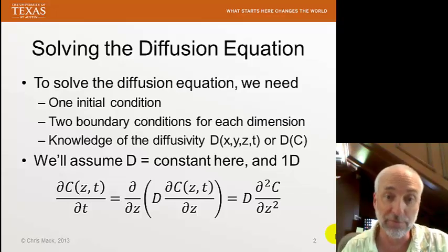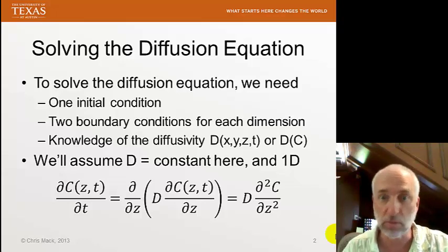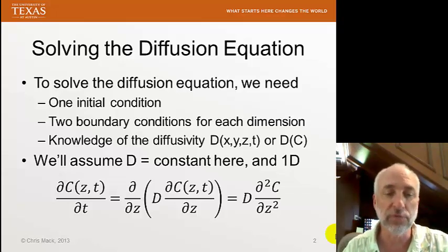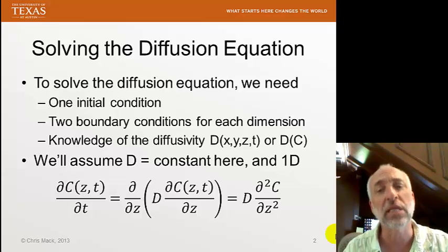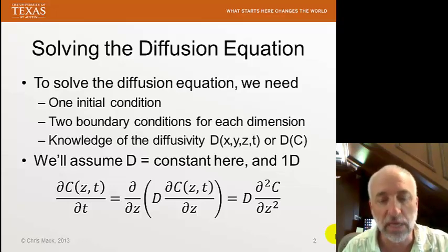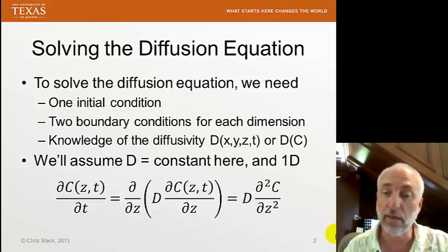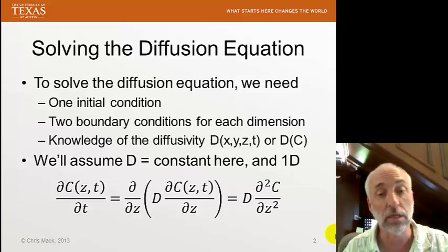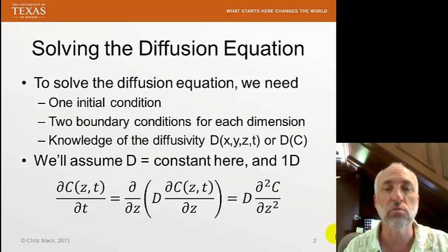Today in this lecture, we're going to make a very simplified assumption. We're going to assume that the diffusivity is a constant. That makes the solutions much easier. As we'll talk about in the next lecture, the diffusivity of dopants in a real semiconductor is not constant — it varies as a function of a number of things. Nonetheless, assuming it's constant allows us to create analytic solutions to the diffusion equation, which are very valuable to know, and they serve as approximate answers to our problem.